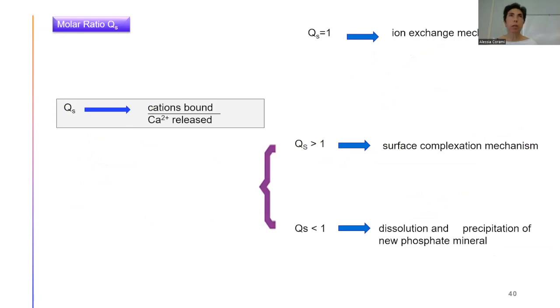Then we study the molar ratio. The molar ratio is the ratio between the cation bound and the calcium released in the solution. So we have a few cases only, when there's lead as the only contaminant, with an ion exchange mechanism, but mainly we have these 2 behaviors. So we have a value that is over 1, meaning a surface complexation mechanism, or a value lower than 1, which means a dissolution and the precipitation of a new phosphate mineral.